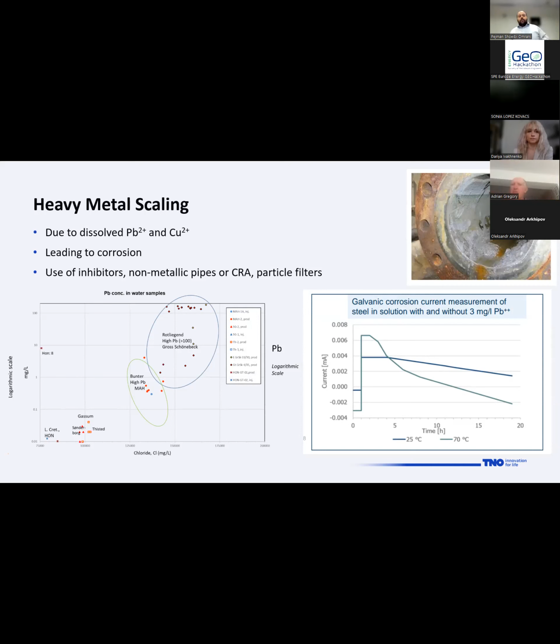The other type of scaling is what we call heavy metal scaling. This has to do with having some dissolved lead or copper in the system. I show you some of these low enthalpy geothermal systems in Denmark, Germany, and the Netherlands, and the concentration of the lead which they are producing. But one thing which is very tricky about this type of scaling is that if you get this scaling in the system, then this deposit will create a medium which will lead to galvanic corrosion, because you will get two different metals in contact. So when you get the lead being formed on your metal, you get lead on top of steel, and that can lead to galvanic corrosion. So it's a very tricky one to deal with.